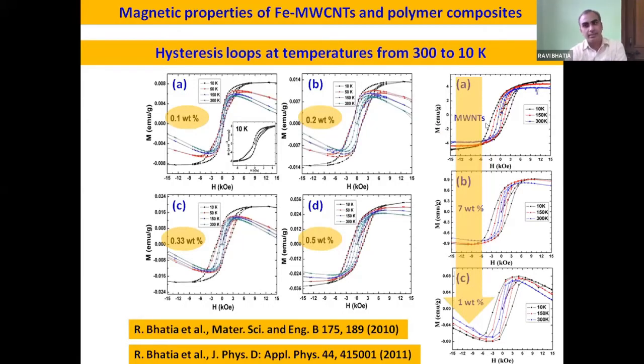The idea is, if you have a bulk sample, you have more magnetization value, fine, there is no problem, because iron content is more in the bulk sample. But the coercivity increases till 1 weight %, and then it decreases, and this thinning or narrowing of the curve is probably because of the anisotropic nature of the iron nanoparticle.